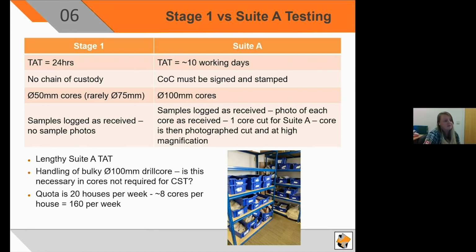It's a big process. The handling of bulky 100mm drill cores is actually backbreaking work when you have so many. We have a quota to meet, which is usually about 20 houses per week. So at 8 cores a house, it's about 160 per week. It all adds up, and then you get these lengthy turnaround times when we get backed up. So maybe, is it necessary to have 100mm diameter cores if they're not suitable for CST? That's something to maybe think about.